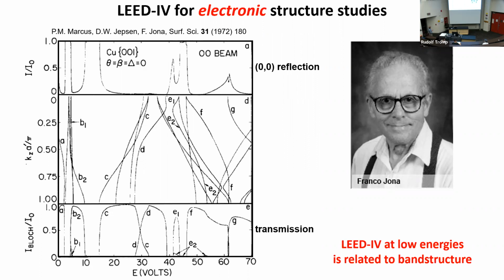And here's the intensity of the diffracted beam, right? And what you see at this energy range here, between 10 and 15 eV or so, the theory predicted that you have a very strong diffracted beam. Basically, all the electrons come back, right? The diffracted intensity is 1. At the same time, the Bloch state inside the solid is 0. So all the electrons come back and no electrons go into the solid.